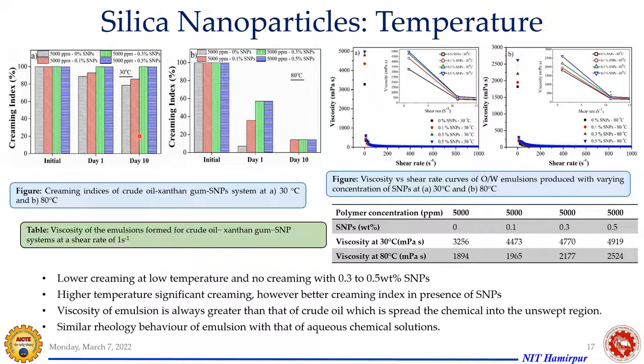And this is the creaming behavior. Okay, so this is a visual observation where you have observed the rate of creaming. And as you see here, this is the very first case. The very first case means at the beginning, the initial day zero, the time at which you have just formed the emulsion. So you can see no nanoparticles. So 0.1 weight percent, 0.3 weight percent, and 0.5 weight percent, three different compositions, and without nanoparticles is what we formed here. So initially, there was no creaming, all were stable.